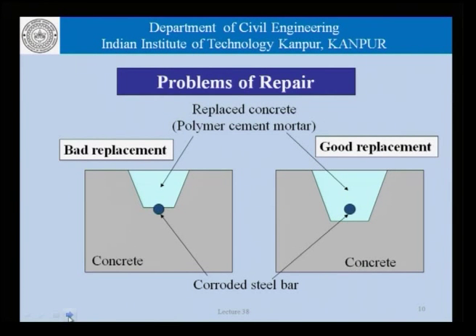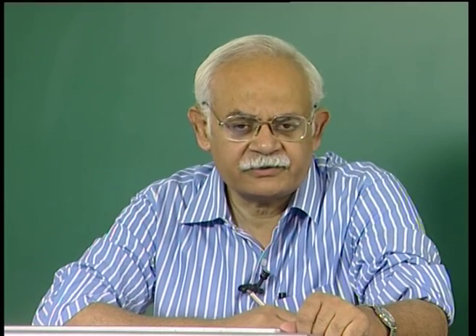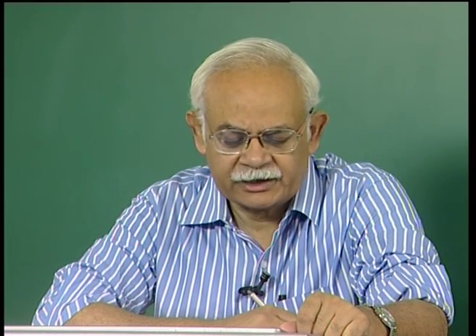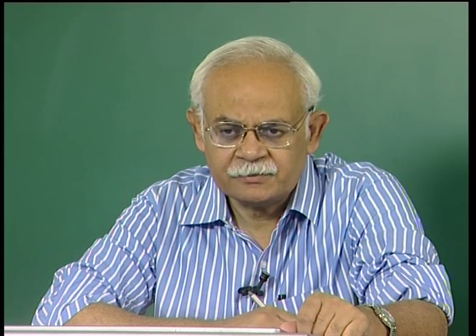We had talked about some problems in repair. We had talked about a bad repair, in which case we had seen that the repair material, for example, polymer cement mortar, is placed in a structure like this without removing all the concrete from behind the deteriorated reinforcement bar, which is what is done here as a good replacement. And a repair action of this nature does not necessarily mean that the structure will not corrode in the future. So, the corrosion or such a problem could manifest itself very quickly after the repair work has been carried out if the work is not done properly.